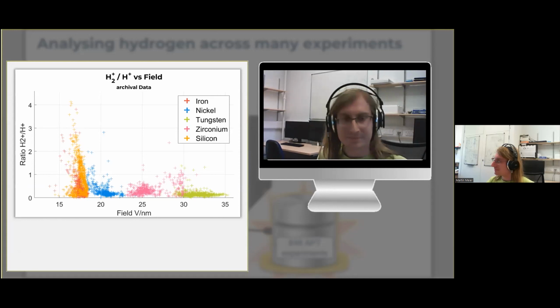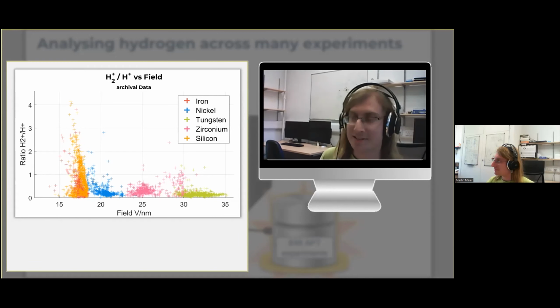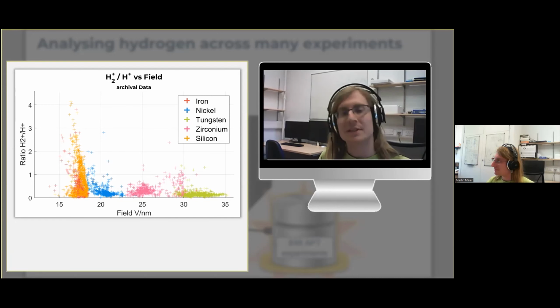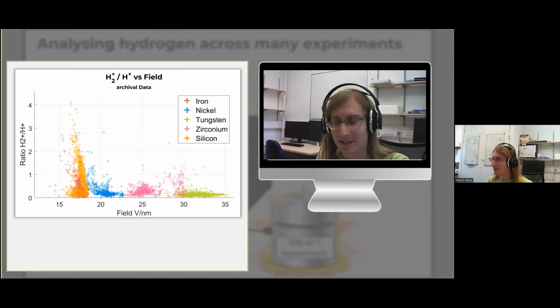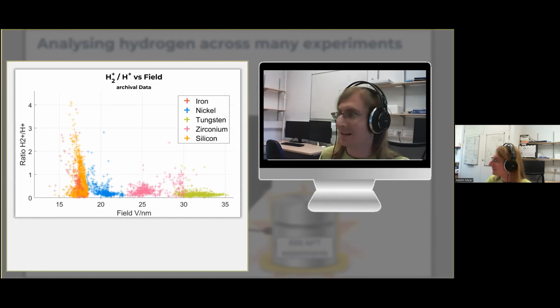In order to get to this diagram, we've done the following. We take a large number of APT experiments, all of them in laser mode, and we slice them along the voltage axis. Then for every experiment and every voltage slice, we calculate the hydrogen ratio and we calculate the electric field, and we add a dot into this diagram. So what you're seeing here is the behavior of the contaminant hydrogen signal across many experiments, across different materials, as a function of the electric field. Cool. So how would you interpret this data then?